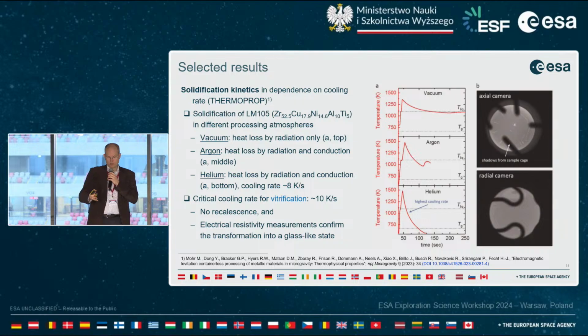In particular, in materials that are glass formers, you can look at critical cooling rates for vitrification and figure that out, and this is about 10 Kelvin per second. So you have no recalescence in this case when you look at the helium-cooled sample, and you can do electrical resistivity measurements, with which you can confirm that there is a transformation into a glass-like state, and that you do not have crystallization in this material.